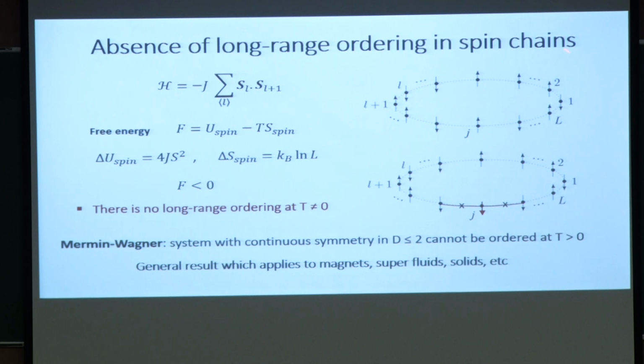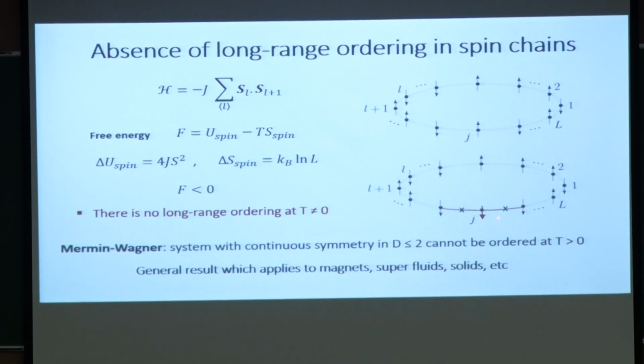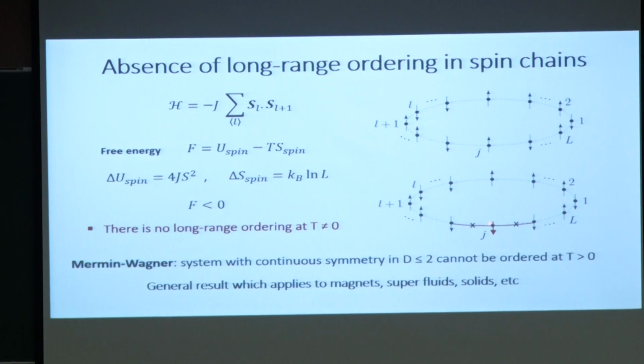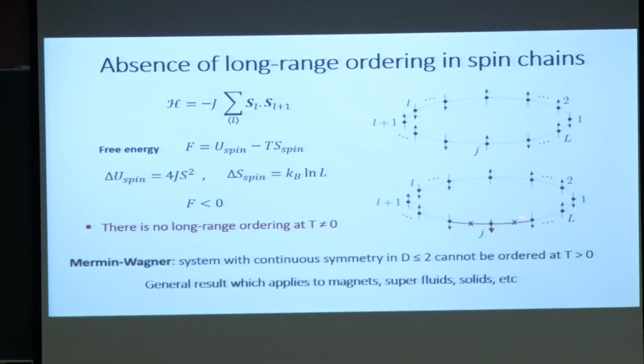So you have this up-down arrangement, and if you disrupt it by turning one of the spins, let's say at the jth site, you will basically make these two bonds unhappy. The consequence is that your U, the magnetic energy, will increase, but at the same time the entropy of your system will increase considerably, because you could have flipped this spin at any one of these sites. All right. So the entropy would scale with the length of the chain.